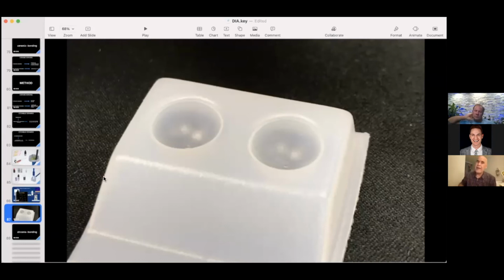So let me give you a little background. When you take your lithium disilicate restoration or feldspathic and you etch it, the surface becomes very hydrophilic. And if you have silanized any of these surfaces after etching, you can see that when you place the silane, it just moves, it spreads out. Why? Because your surface is hydrophilic after etching. But once you apply your silane and your silane reacts with the surface, your surface becomes hydrophobic. Okay, because now your surface has been reacted with the silane. That's a chemical reaction, and you get a hydrophobic surface.